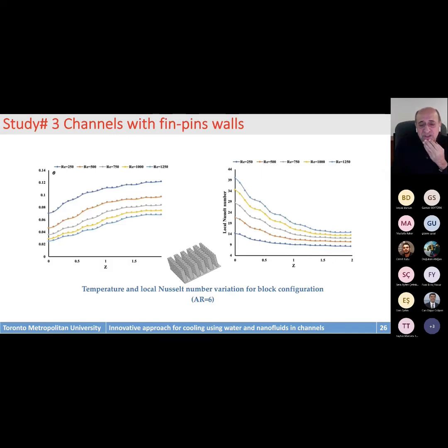The third project which we did is basically, what if we use pin fins? So we measure the temperature at the base of the pin fins, and here you see some crooked profile for temperature, and this is normal. The reason is at the point at the interface below the pin fin, we have a drop in the temperature. Then when the flow circulates between the pin fins, the temperature rises shortly, then drops. So this wavy fluctuation which you see is basically due to the pin fin. So at the pin fin base, we have good heat extraction, then it changes slightly.